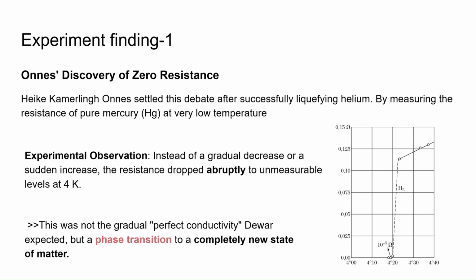there is an inclined line. There are three dots when the temperature goes from the right hand side, around 4.4 Kelvin. The resistance will be around 0.10 to 0.15 ohms. But when the temperature gets close to 4.2 Kelvin, the resistance abruptly drops to around zero, but not exactly zero. It's nearly 5 times 10 to the minus 5 ohms. That proves that this was not the gradual perfect conductivity Dewar expected, but a phase transition to a completely new state of matter.